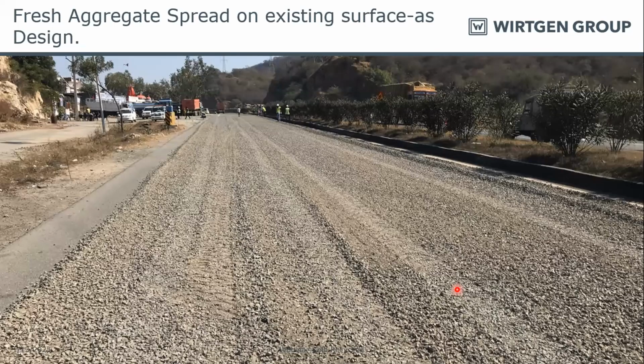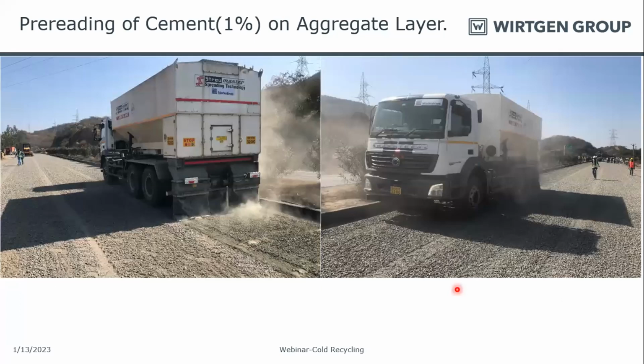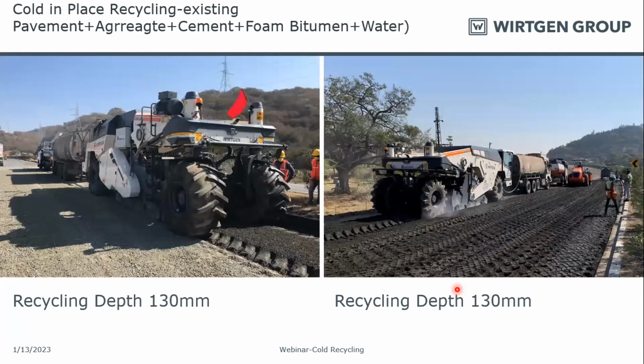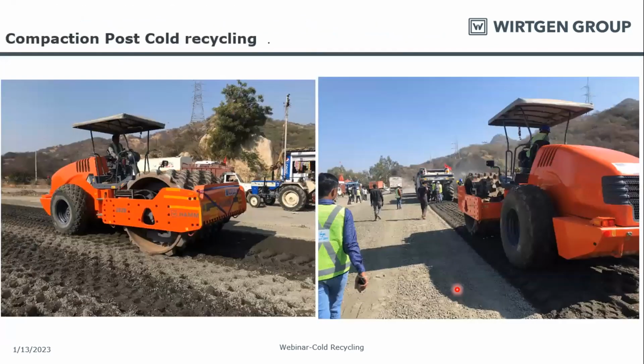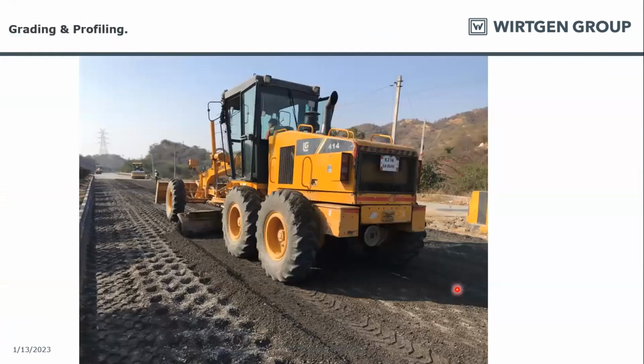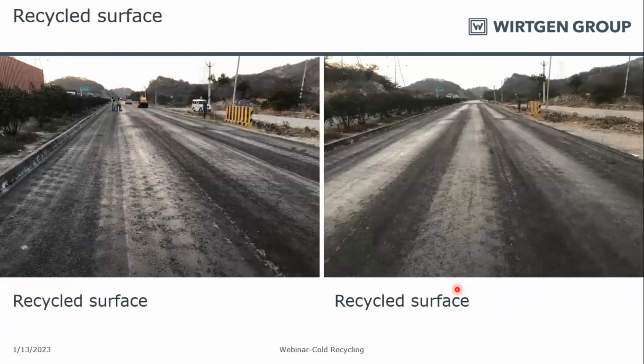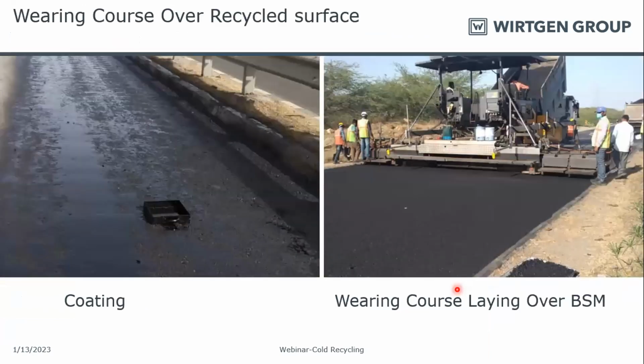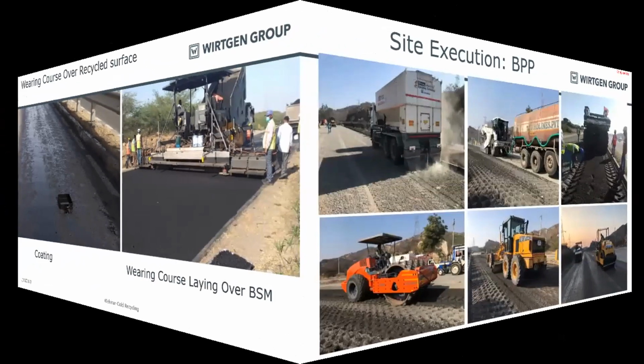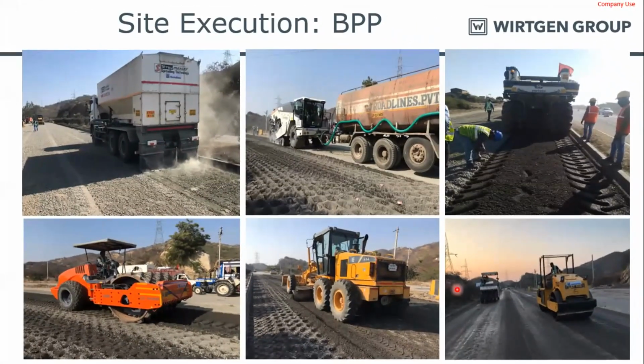These are the fresh aggregates being laid, and then this is the cement spreader. We spread it as per the design. And here we recycled roughly 130 mm. Next we do heavy duty compaction. We grade it to the profile and we get a recycled surface. Then we lay a tack coat and a BC on top of the BSM. We need to cure the BSM layer for 48 to 72 hours before laying the BC layer. These are some of the job site pictures.